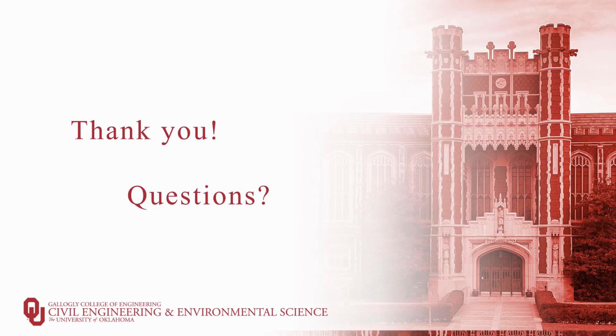So I kind of mentioned it previously during the presentation. The UHPC has a shorter transfer length, so reducing the beams from 18 to 14 feet long did not really have a big impact, especially since the UHPC has the shorter transfer length compared to conventional concrete. I think that's one of the main reasons why we wanted to go from 18 to 14: this material can be eliminated without having any comparable issues between the hybrid and the UHPC.